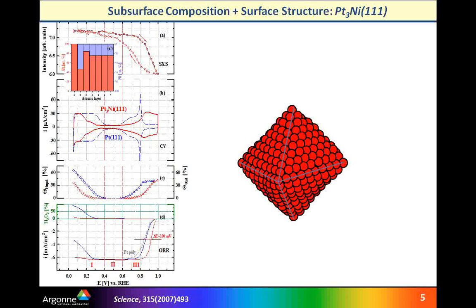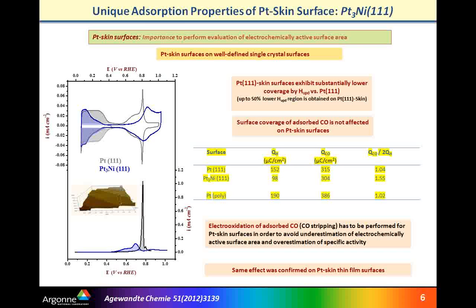Now, once we have defined the platinum skin structure, and in this particular case for platinum single crystals, it is actually very easy to establish, for example, how many active sites we have, because electrocatalysis, especially specific activity, is based on the number of active sites, or if you like, the turnover frequency for the reaction.